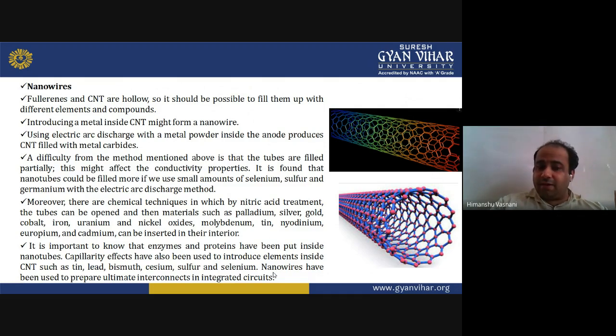Moreover, there are chemical techniques in which, by using nitric acid treatment, the tubes can be opened. And then materials such as palladium, silver, gold, cobalt, iron, uranium, and nickel oxides, molybdenum, neodymium, europium, and cadmium can be inserted in their interiors. So we have these techniques: by using nitric acid treatment, these tubes can be opened, and then materials such as those listed can be inserted in the interiors.